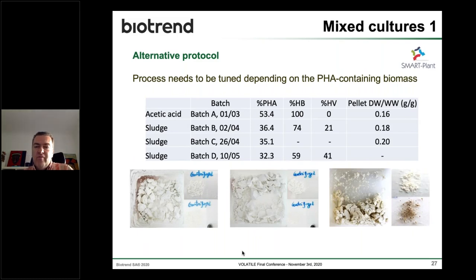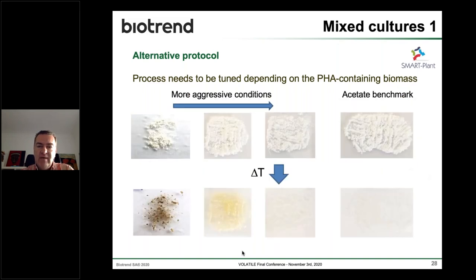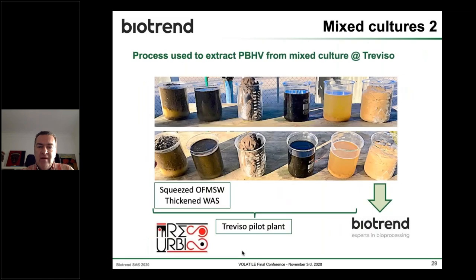So the process worked very well, although it needed to be fine-tuned depending on the PHA-containing material that we were receiving. So there's always an optimization which needs to be performed depending on the biomass that we get. And the dirtier the sample, the more aggressive the conditions that we need to use, of course. But after some optimization, we can actually purify polyhydroxyalkanoates from real-life scenarios.